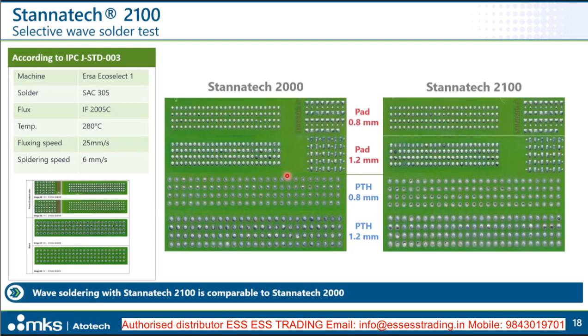Also here we have test structures on our test boards where we have PTHs with different diameters and also pads with different pad sizes, which are then immersed or exposed to the liquid solder. What we evaluate here is whether any PTHs are not fully filled with solder, and that all the rectangles or the rings are fully covered with solder. And also here we don't see any difference between the Stannatech 2100 and the Stannatech 2000, so it performs well.